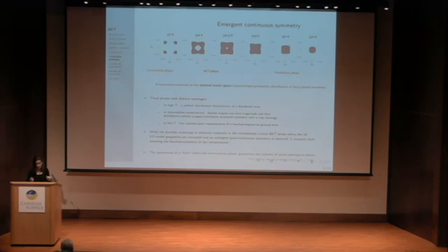So we have, for that, computed the symmetrized probability distribution of the local dipole moments, which is basically the internal state space, and we've checked the evolution of its topology with decreasing temperature. So as you can see, we are in presence of 3 distinct phases with 3 distinct topologies.